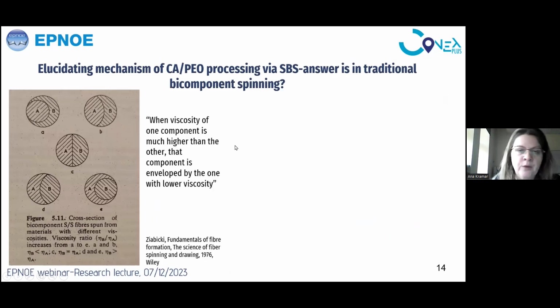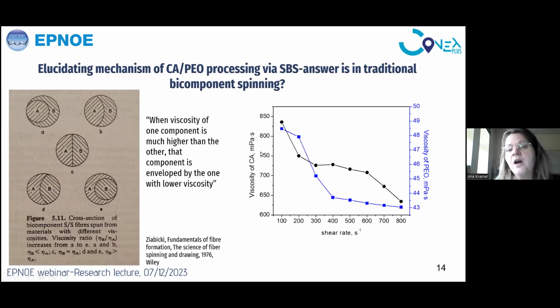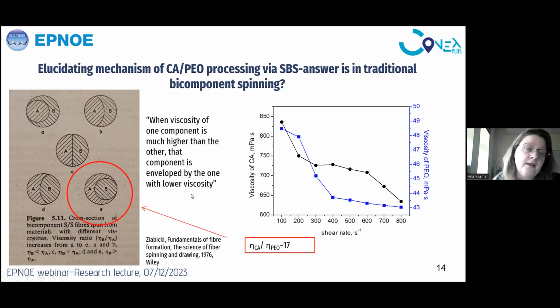And I will quote: when the viscosity of one component is much higher than the other, that component is enveloped by the one with lower viscosity. So we measured the viscosity of our starting polymer solutions, cellulose acetate and PEO. And here you can see that their ratio is really high, and that the viscosity of the cellulose acetate that we used is almost 17 times higher than that of PEO. So it means that most probably this is the answer why we have the dark coating of polyethylene oxide that surrounds the cellulose acetate component and helps the spinning.